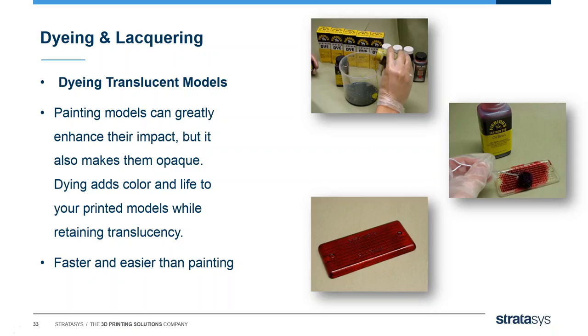You can mix different colors, so you can achieve more or less any needed shade of your color, and pour it with cooked water, and then bring the parts on a hook into the water, and then it's a question of time to have a light red, like this example here, or a darker one, or a middle intensity of color. This is a question of how long you keep the parts in the warm or hot water. It should be hot, but not cooking anymore.